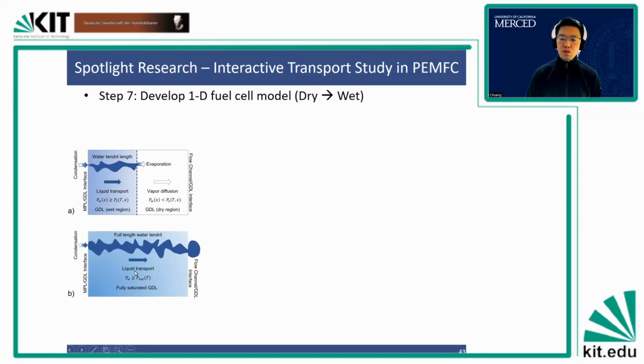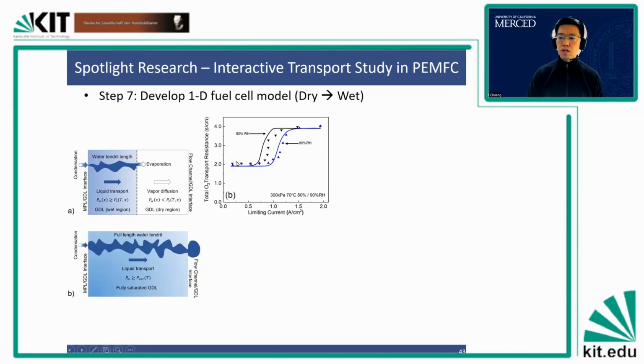And based on this physics of the tendril model, we were able to predict. The black line is model prediction. The symbols are experimental measurement. So we were able to predict this transition from dry to wet in the gas diffusion media.